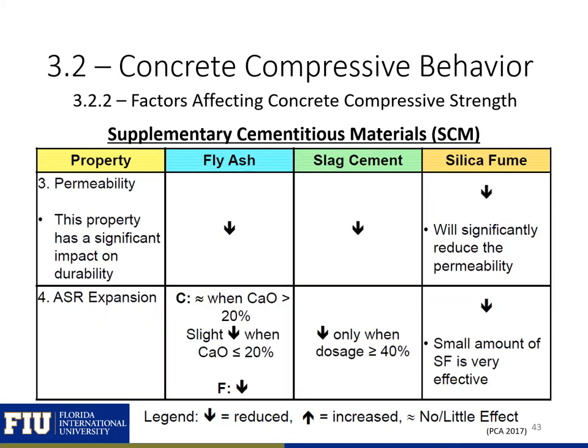The main benefit of SCMs is in terms of long-term durability. Fly ash, slag cement, and silica fume will all decrease the permeability. A decreased permeability means that the concrete will be more resistant to corrosion, as it will take longer for chlorides to reach the level of the steel.